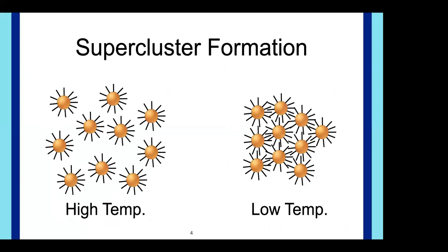The basis of the supercluster formation: at higher temperature, we have our monomer units separated in solution because of the higher solubility at higher temperatures. At lower temperatures, we reduce the solubility. These are going to assemble together into agglomerations, hopefully spherical. This could be done through intercalation of the ligands, kind of shown here, the alkane thiolate ligands interacting, or through gold-gold interactions from the surfaces, which you could get from the nanoclusters that you probably couldn't from the nanoparticles, because their surfaces are much more flat.